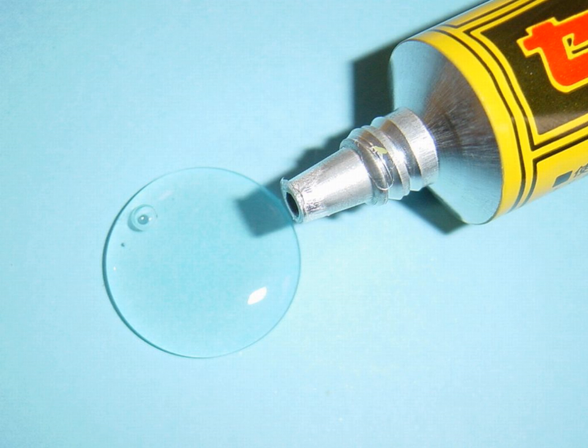Topic: Methods to improve adhesion. The quality of adhesive bonding depends strongly on the ability of the adhesive to efficiently cover, or wet, the substrate area. This happens when the surface energy of the substrate is greater than the surface energy of the adhesive. However, high-strength adhesives have high surface energy. Thus, their application is problematic for low-energy materials such as polymers.